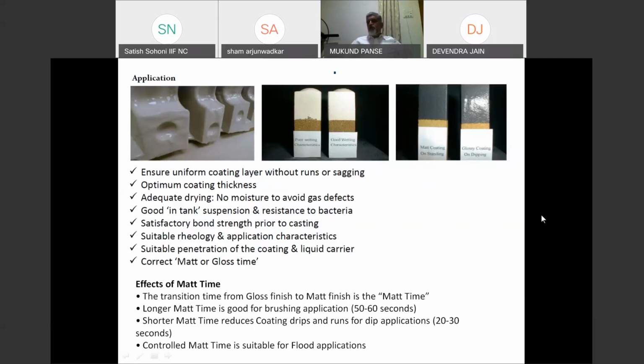When you coat the paint or dip, firstly you get a glossy surface, and after the paint is completely either slightly absorbed in the coating or gets dropped, you get a matte finish. What you are trying for is a matte finish and not a glossy surface. A glossy surface is likely to peel off if it remains glossy and thick like that. Longer matte time, the time from gloss to matte, is good for brushing applications. Shorter matte time is good for dip coating to avoid runs.